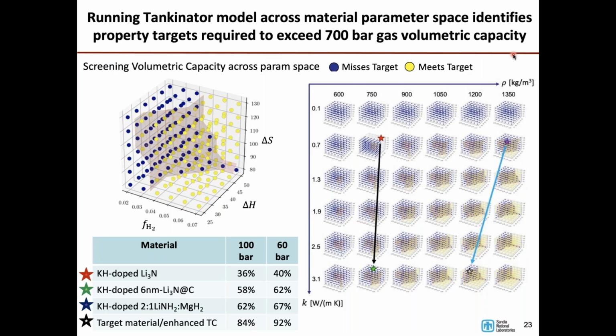And then we do that, so that three-dimensional calculation is expanded to include the density, so that's over here on the right, in the horizontal axis, rho, kilograms per cubic meter, and the thermal conductivity, kappa, on the vertical axis. So you can see here that there were actually thousands of calculations that were done to map out this parameter space. We actually automated the Tankinator code so that this could be done quickly. What you see is that the canonical baseline material, this potassium doped lithium nitride, this little red star up there, you can see that its density and its thermal conductivity are both too low to meet the target.